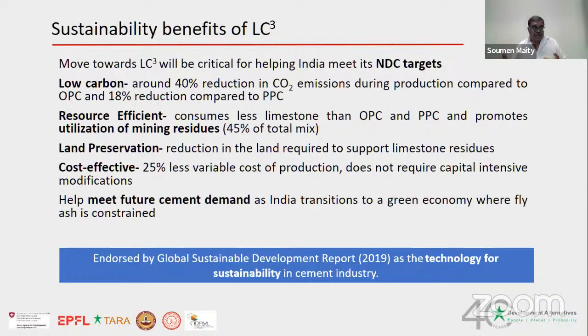Resource efficient, yes, of course. Of the composition that we have, 15% is crushed limestone that is not cement grade limestone, which is otherwise being wasted. We don't call it a waste. We say that it is a non-commercial grade material. And the calcined clay that we are using here is also not of ceramic grade. That's a waste clay. Professor Scrivner already pointed that out. So in that total mix, we have roughly around 45% of non-cement grade or non-commercial grade raw materials. And if we are using up waste materials and the waste limestone, then it is going to help us in preserving our land.